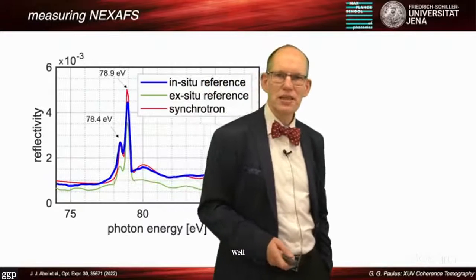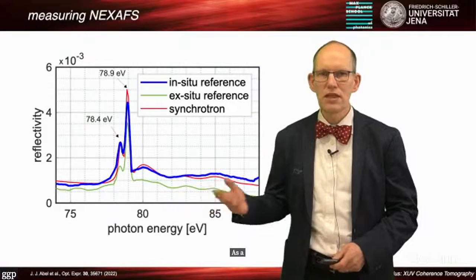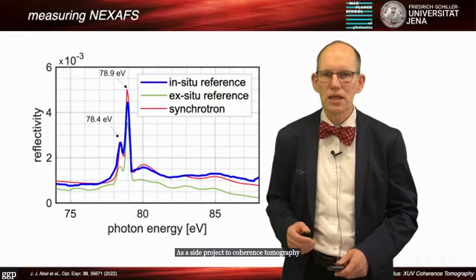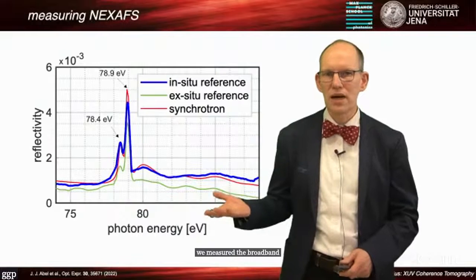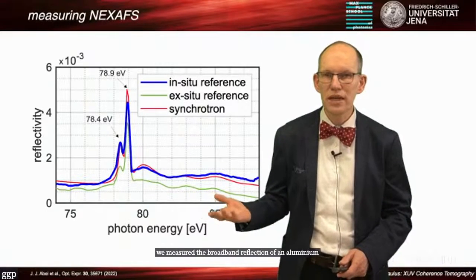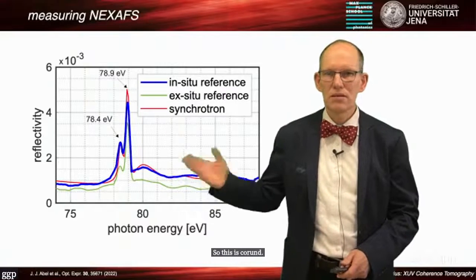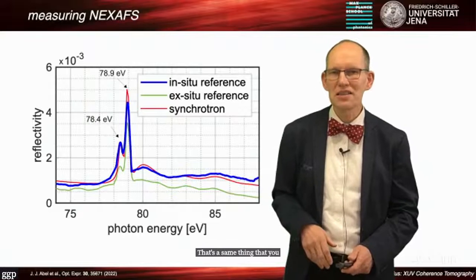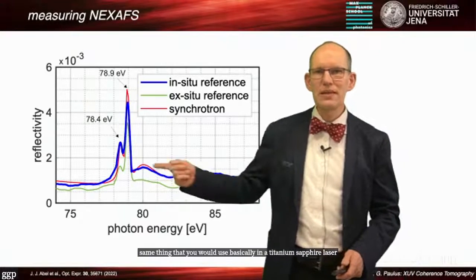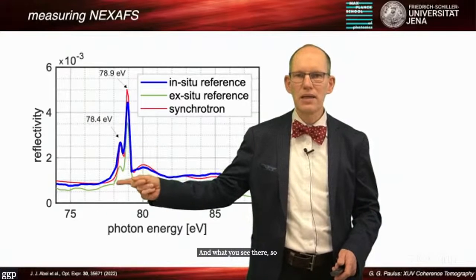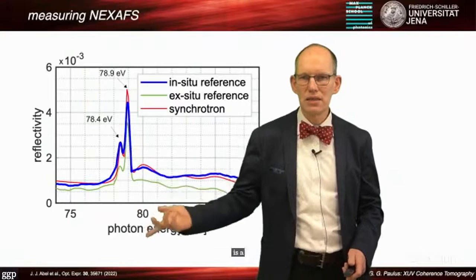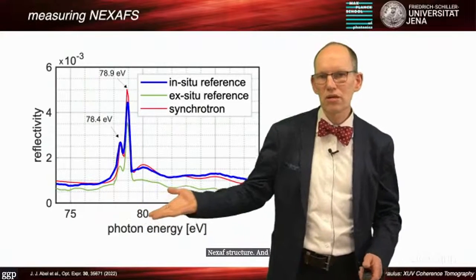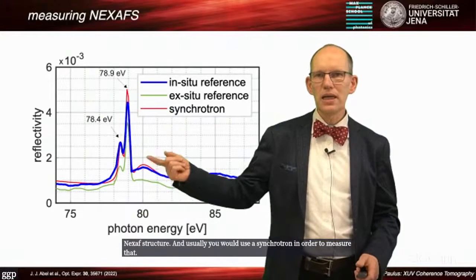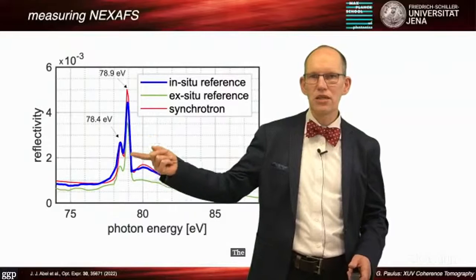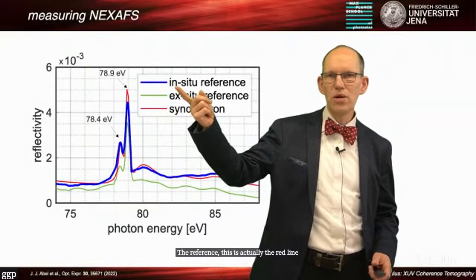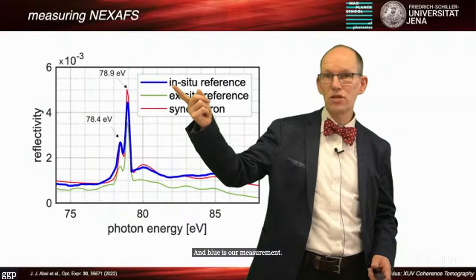Well, just to illustrate my point, as a side project to coherence tomography, we measured the broadband reflection of an aluminum oxide substrate. So this is corundum. Same thing that you would use basically in a titanium sapphire laser, right? And what you see there, just below 80 electron volts, is a prominent NEXAFS structure. And usually you would use a synchrotron in order to measure that. And what you see is the reference. This is actually the red line, right? And blue is our measurement. And you see virtually perfect agreement.